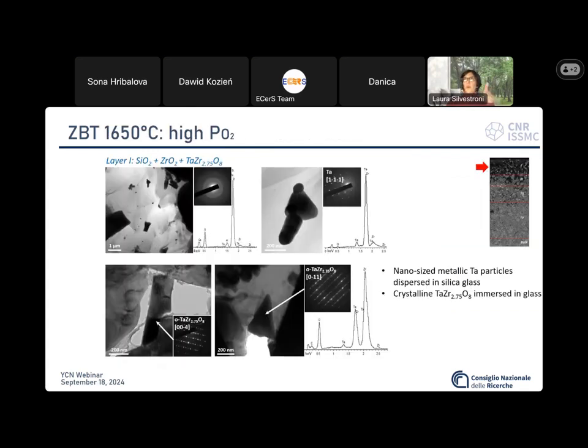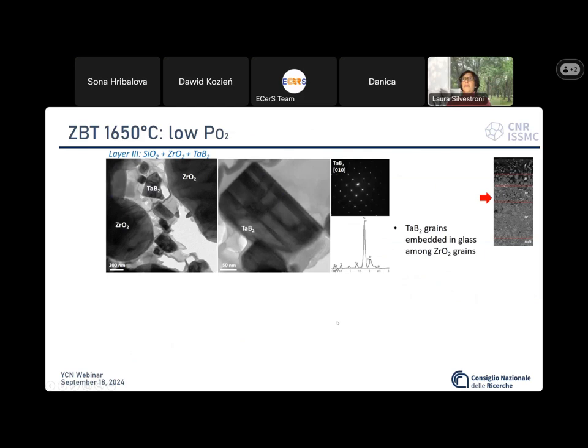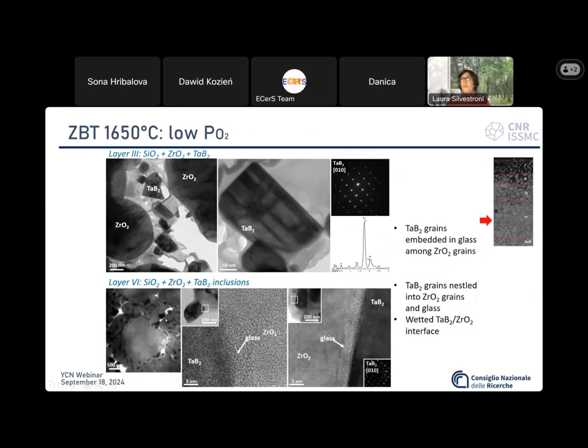But if we go deeper and check each layer by TEM, with a lot of patience and luck, maybe you can recognize, let me just jump to the point, you can recognize in this structure our core shell structure. So actually zirconium diboride oxidized into zirconia, and our tantalum non-inclusion reacted with the boron oxide released by the matrix and formed tantalum diboride. So far so good. By oxidation we form a boride, good.